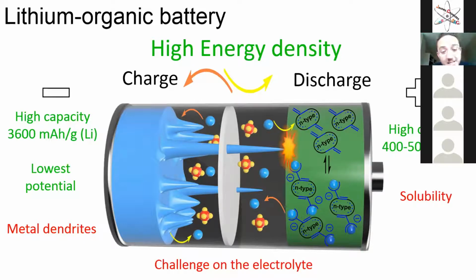Why? Because based on the electrolyte that you use, when you use lithium metal as anode, you start growing what we call lithium dendrites. This is the kind of thing that you see growing on the surface of the anode on the left. Then it goes through the separator and touches the organic electrode. If you have that, you generate an internal short circuit, and this causes the battery to heat up and then to explode. For the cathode, those cathodes that can provide 400, 500 are mostly soluble in organic solvents. So after the second, third cycle, you will have no more cathode, and the battery will be dead.